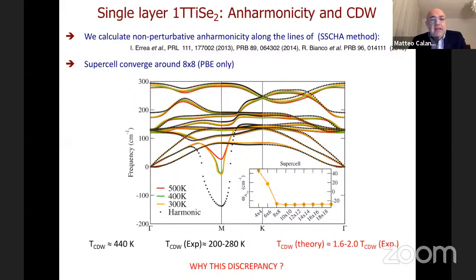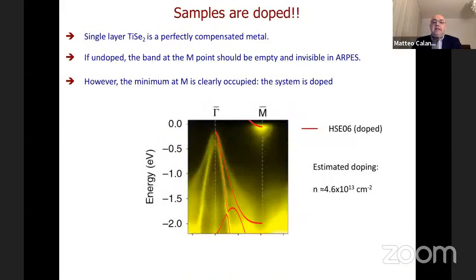But still, it's bigger than in experiment. So can we do better? And is there a discrepancy or is this an error? So one possibility is to consider the fact that the samples are doped. This is not the only possibility. One possibility, for example, would be that the samples are strained by the substrate. However, due to X-ray diffraction, we know the lattice parameter of the single layer, and the lattice parameter is exactly the same that we calculate, and it varies not substantially between PBE and HSE06.